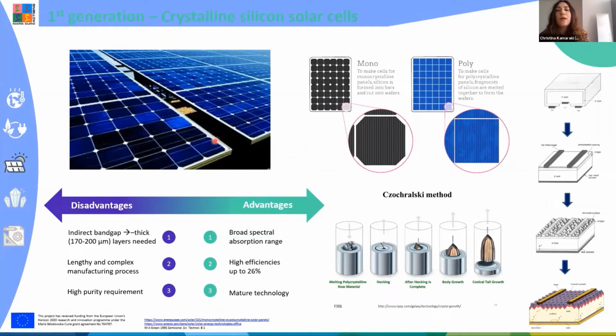Crystalline silicon solar cells are made of silicon wafers, which are really thin pieces of silicon. The fabrication of silicon wafers is a high temperature procedure. So first we melt the silicon, and then we create elongated crystalline bars, and then we cut them in really thin pieces. We have 2 different types of crystalline silicon wafers. The monocrystalline silicon, which come from a single crystal of silicon, and that justifies its shape. So as you can see, it's polygonal, and that's why we have these gaps in these monocrystalline modules.